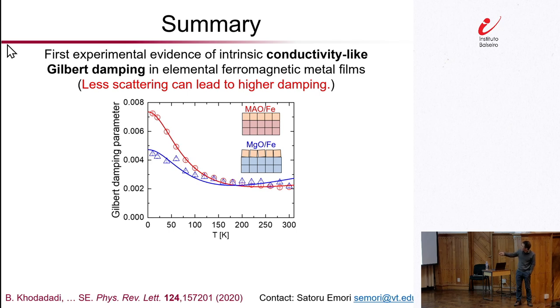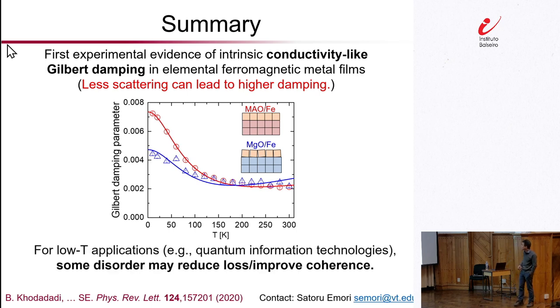The most striking finding about this is that you can have a higher amount of dissipation or damping in the presence of less scattering, less disorder. So I hope you find that to be fundamentally interesting from the basic science point of view, but we also argue that this is important for some of the emerging lower temperature applications, let's say for quantum information applications, or even just interfacing magnetic devices with superconducting devices at low temperatures.